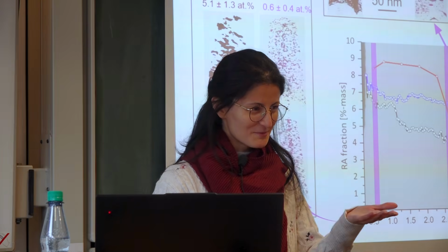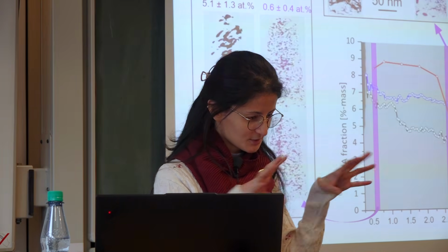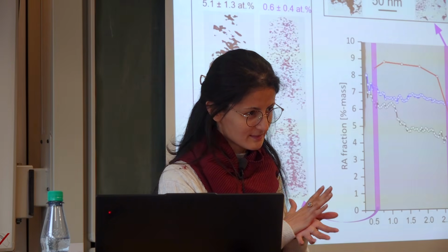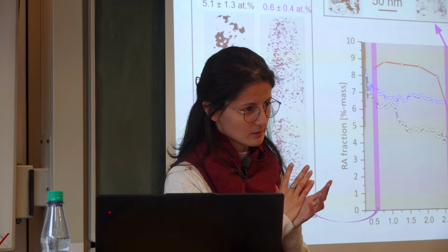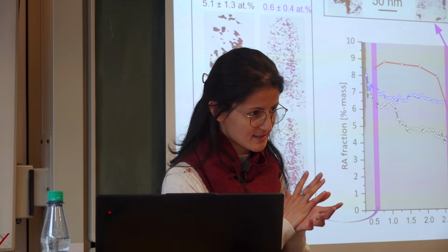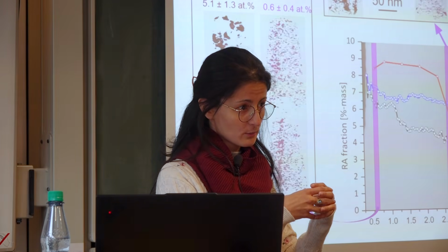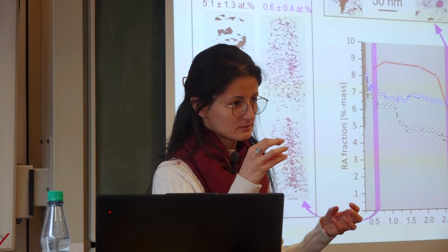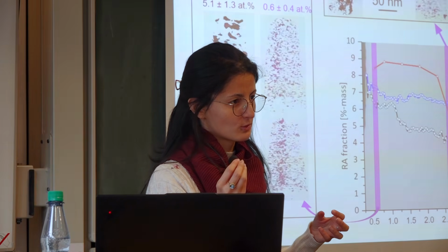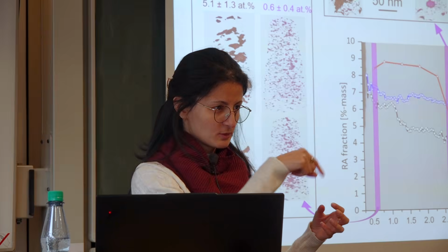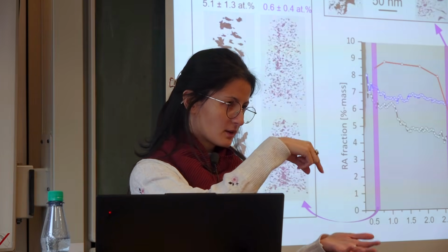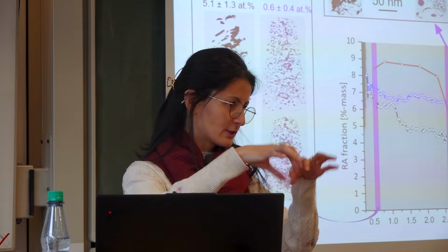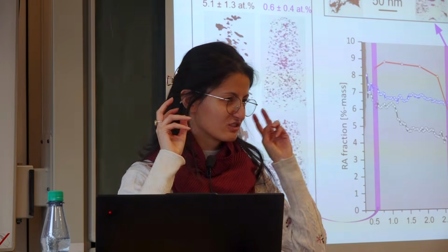So we had this problem actually recently. We had these powder samples. We needed to compact them very much so that we would reduce the porosity inside. And then from this packed sample, we extract samples for atom probe tomography. So with the ion beam, we cut all around, and then we put them on this silicon post that I showed, so this little kind of pyramid.